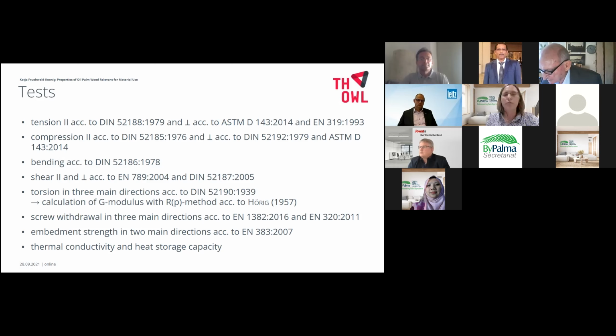In the context of two research projects, the elasto-mechanical properties of oil palm wood were systematically tested on small size test specimens: modulus of elasticity and modulus of rupture in bending, Young's modulus and strength in tension and compression, torsional strength, shear strength, screw withdrawal and embedment strength, thermal conductivity and heat storage capacity. Due to the time limit today, I will concentrate on the tension, compression and bending properties parallel to the vascular bundles, but all results will be published soon.